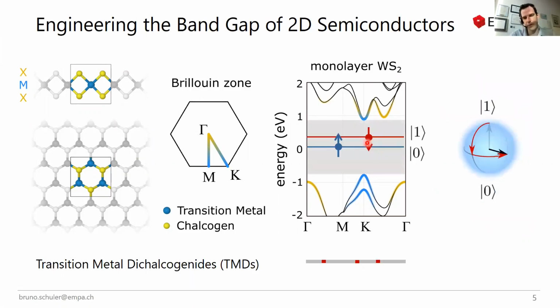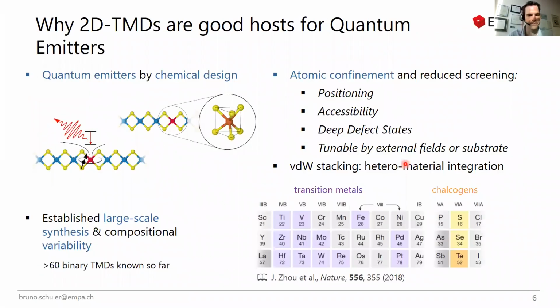What our research is mostly concerned about, however, is how to design the band gap in this 2D material by introducing dopants, which themselves have discrete energy states that may be spin polarized, and then play around with these states. In the long term, we're trying to coherently control their properties and the excited state dynamics of these states. But the first step is trying to understand what type of defect creates which type of energy manifold, and select the more interesting ones from those which are just detrimental to the material.